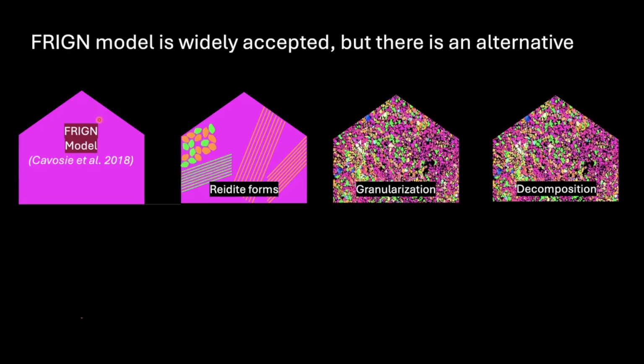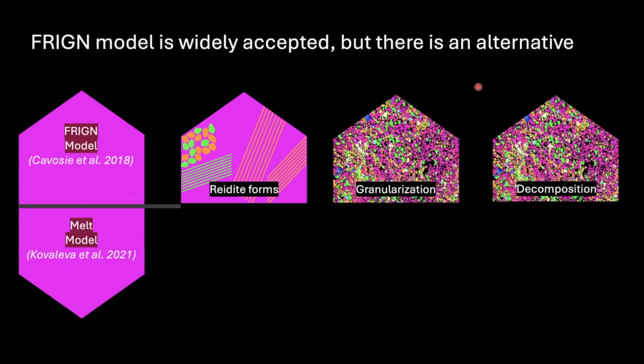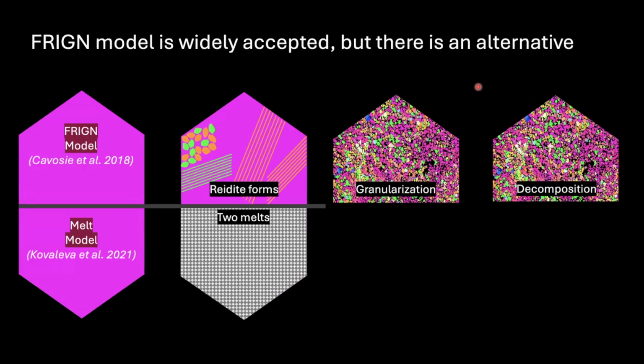So here's another version of that widely accepted mechanism, but this is with my own data. There's an alternative model out there from Lisa Kovaleva. So in her paper in 2021, she proposed a melt model. In her model, she says you don't have to make Reidite. What happens is instead of the really high pressures to make Reidite, you get extremely high temperatures to the point where zircon fully dissociates into 2 immiscible melts. One is a zirconia melt and one is a silica melt.